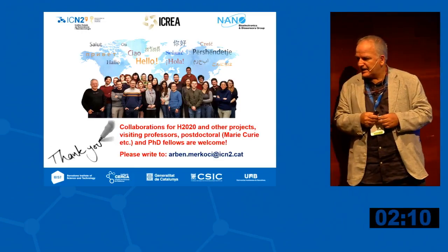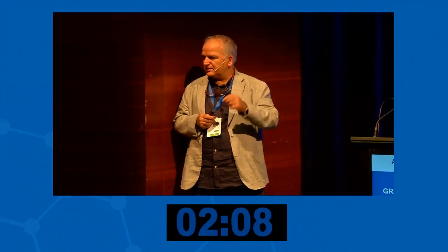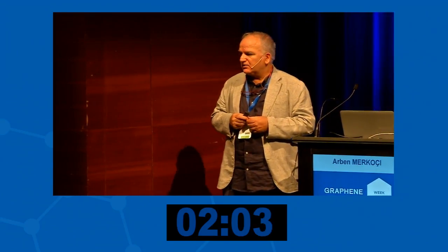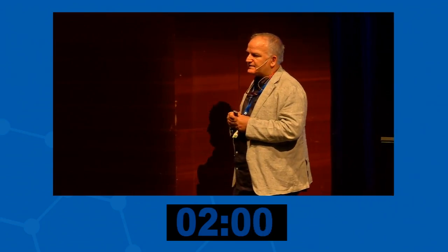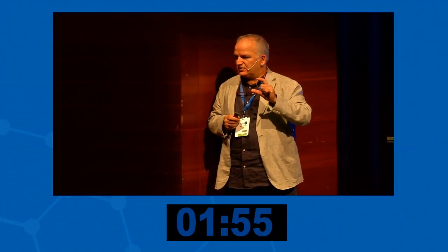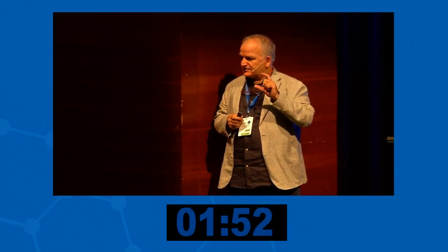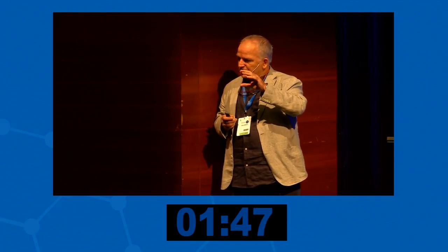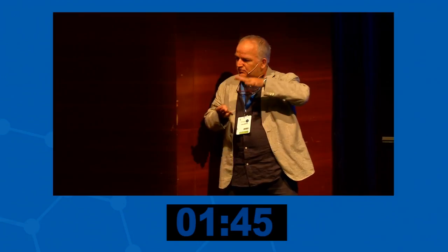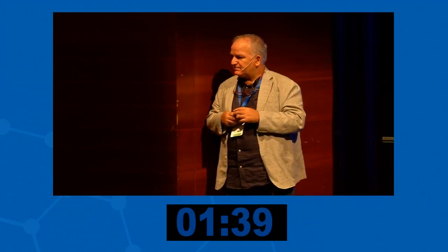It depends on the kind of quantum dots you are using. In fact, we have been working with cadmium selenide quantum dots of around 2 nanometer size. In our case, we have these quantum dots modified with antibodies. Imagine the kind of receptor you are putting, and of course the size is very important, because this quenching will depend on the distance between the quantum dot and the graphene. So whatever you put in between will affect the distance between these two. So this depends very much on that.